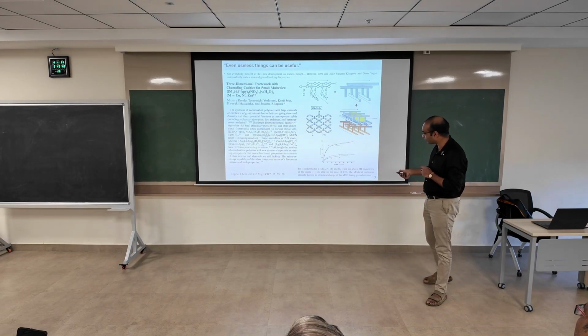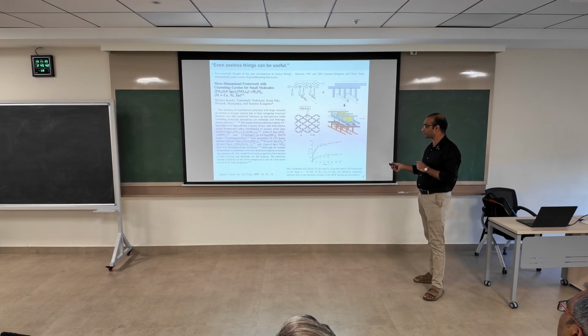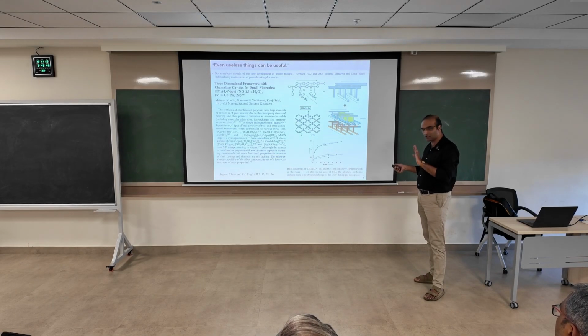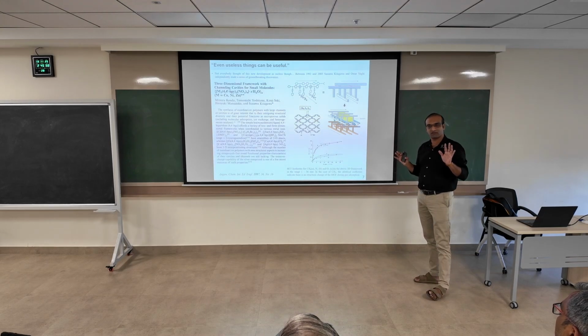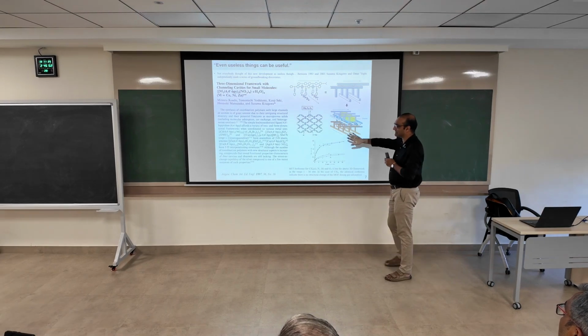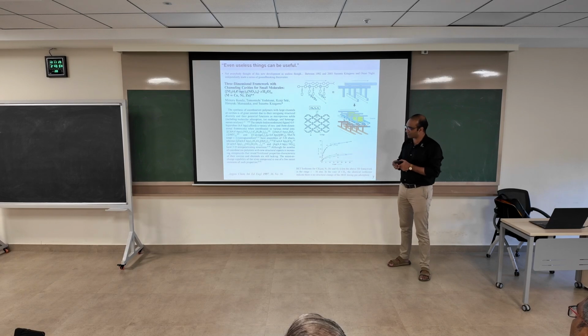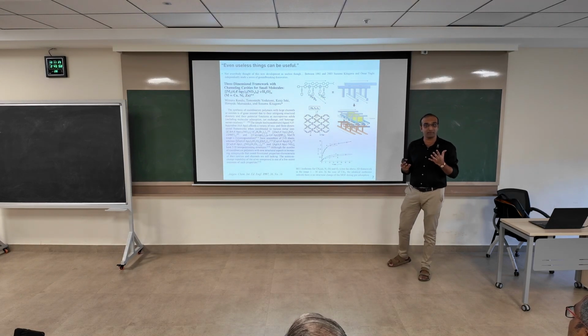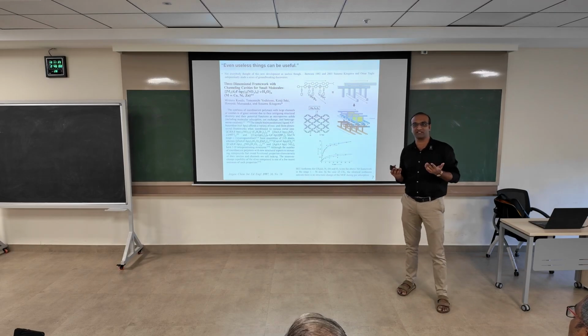Especially in the case of CH4, if you look at the adsorption isotherm, once it accepted the gas and once the gas desorbed, it was still okay. And when they did the XRD for it, the structure was still the same. So this is the first instance where Kitagawa showed that these morphs can be made more stable than what was previously known.